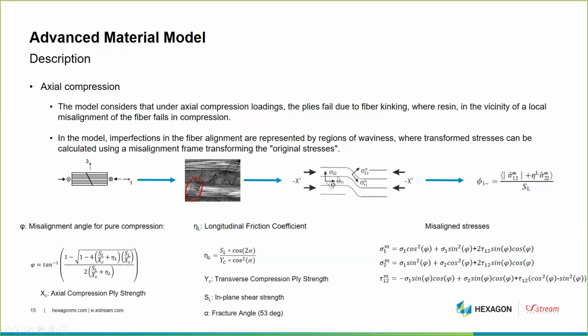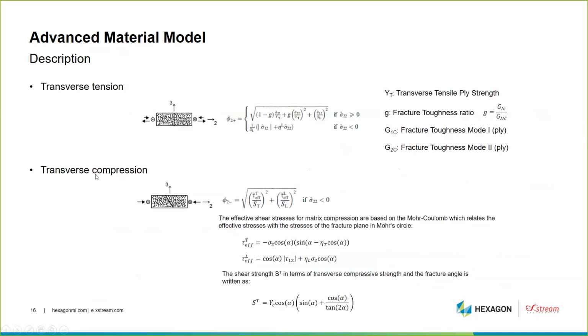So once the misalignment angle has been computed, then the stress can be rotated into the misalignment frame, and the failure criterion can be computed using those rotated stresses. For transverse tension and transverse compression, we always have a combination of the transverse stress, sigma 2, with the in-plane shear stress. So that's the case for the transverse tension, and also for the transverse compression.